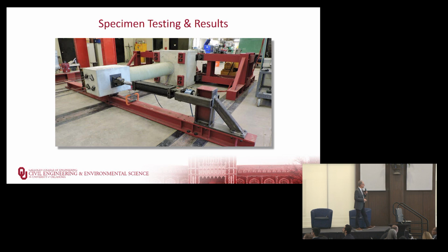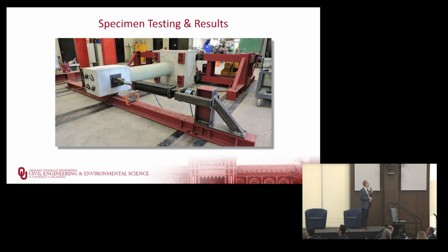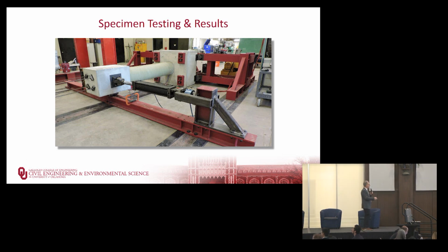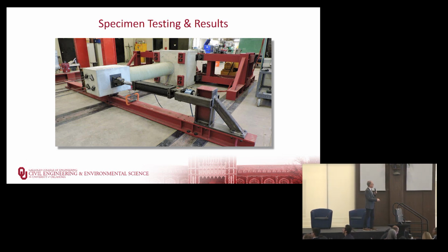So here's one of the specimens in the frame getting ready to test. You see the crimson frame here in the back. This is our base. We've anchored it with high strength rods. This is the column test specimen, the loading stub. These are the pre-stressing strand that apply the axial load. And then this is our hydraulic actuator. It's a push-pull actuator, so we could push it in each direction, then pull it back in the other direction. And then this is our 100 kip load cell.